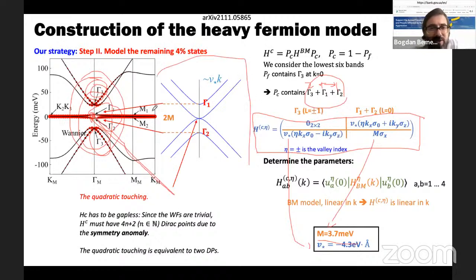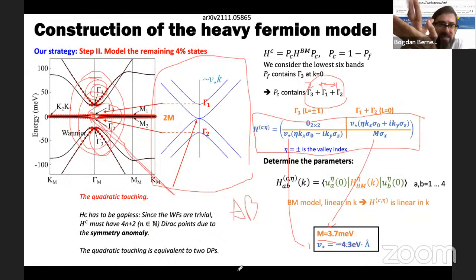Now, you can remember that the band structure of this is the band structure of AB untwisted bilayer graphene. Right? If I take AB Bernal stack graphene, I will get a double Dirac node at the K point. And this double Dirac node is this gamma 3 representation. This is the double Dirac node, and these other gamma 1 and gamma 2 are the extra bands. So this is exactly the low energy model of the AB untwisted bilayer graphene. So now we've solved the topology problem.